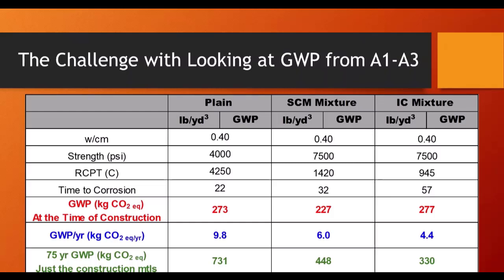We are not considering the fact that the concrete is going to be out there to do something which we've designed it for. And if we start to figure in a 75-year period and we look at the equivalent kilograms of carbon dioxide, I didn't do all the service life modeling yet, but we look at these, we see a very different evaluation of these mixtures. If we take the global warming potential and divide by years, we see we're way down about 40% when we start to talk about that internally cured mixture. If we look at the bridge over this time period, NDOT would have replaced this bridge by about 2.5 times over that period, where the internal curing bridge, we use one bridge.